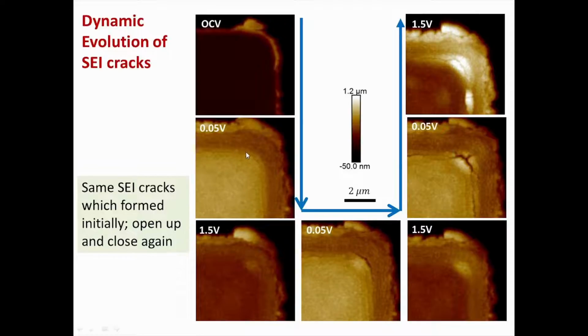So what you could see is that in the first cycle at 0.05 volt, there are some cracks appearing in the edge and corner sides, but these same cracks evolve further as we go to the second cycle lithiation at 0.05 volt. So the same cracks which form initially open up and kind of close again. This also proves the point that these SEI cracks don't fill up with new decomposition products. They remain open in some form of nanochannel cracks, which we could study with AFM.